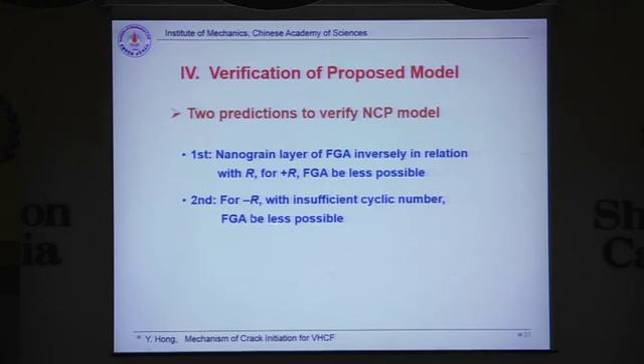And the second prediction is that even for a negative stress ratio, for example, -1 stress ratio, if the loading cycles are not sufficient, this type of fracture surface with fine microstructures will also be less likely.